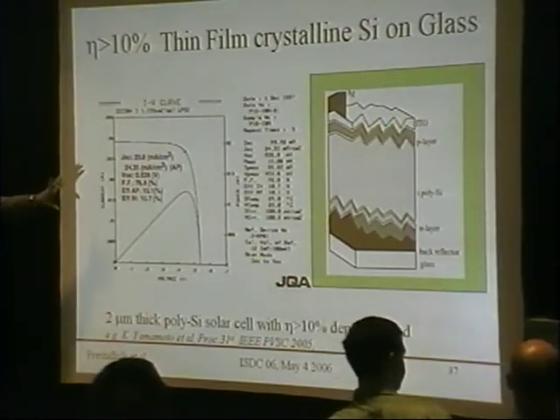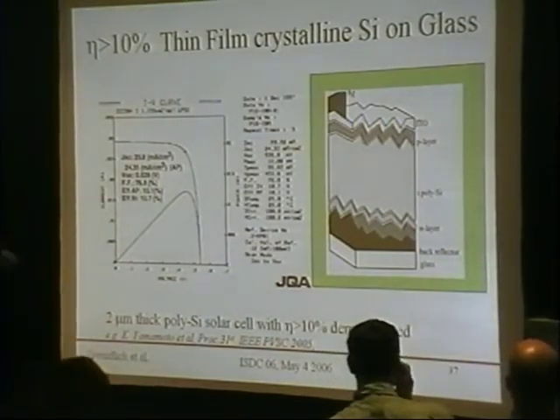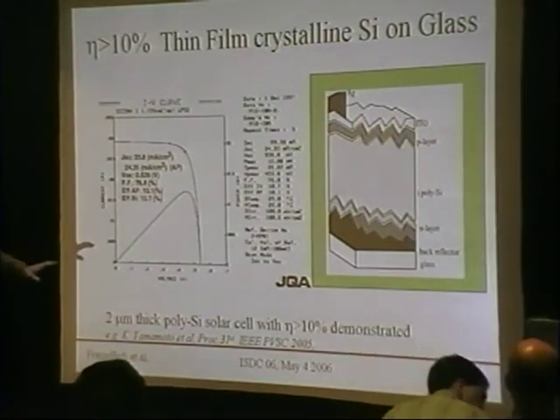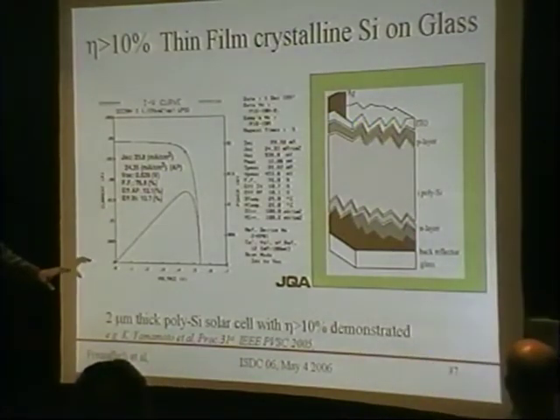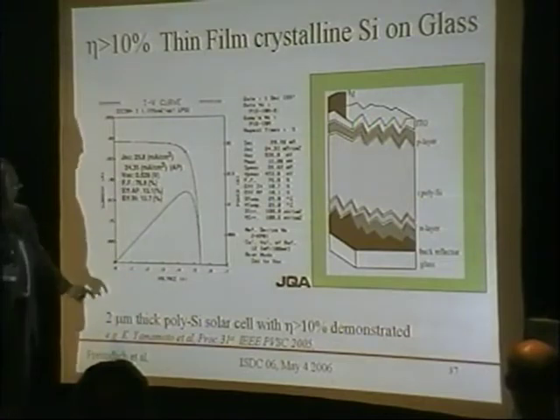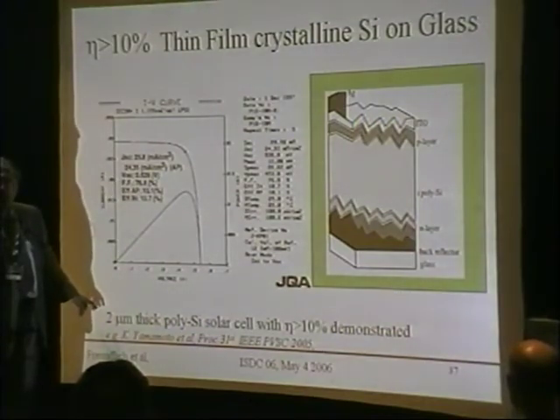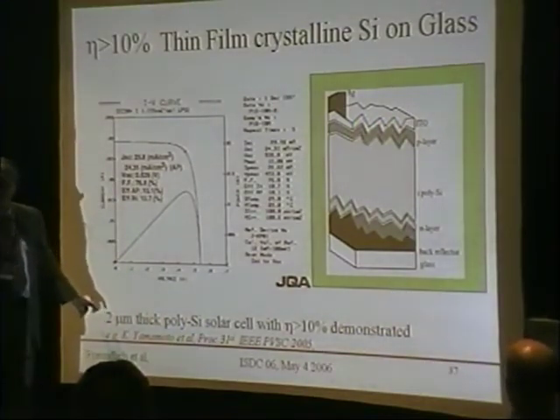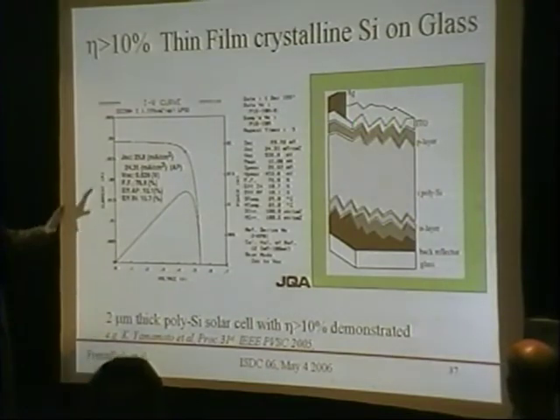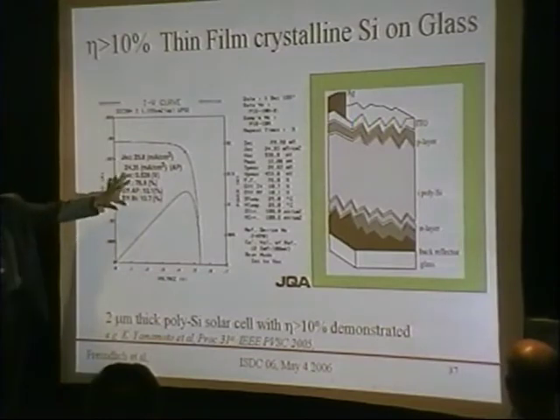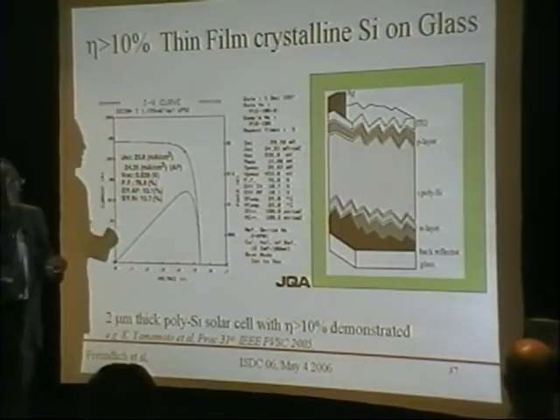This is an experimental result from Kaneka in Japan, showing a 10% efficient cell. This is actually not space 10%. It's terrestrial 10%, which is probably 8.5% or something like that. Nevertheless, strangely, it's 2 micron thick. I don't know what the grain size is in that, but it shouldn't be far from 1 micron.